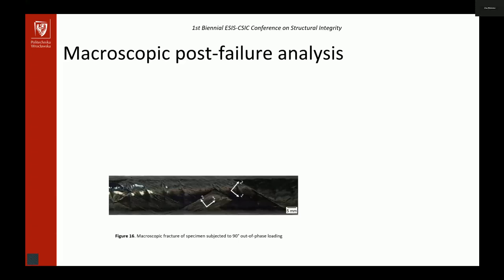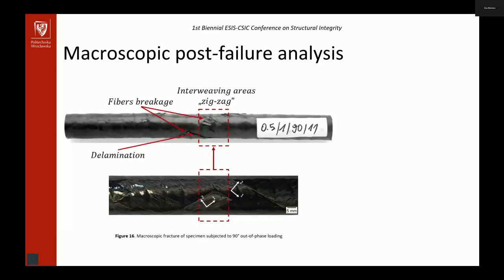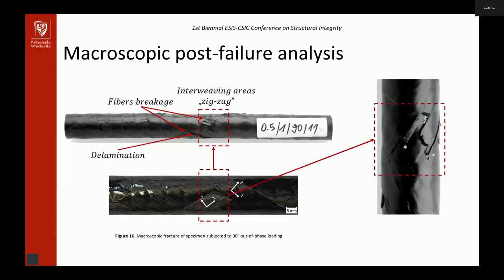Now we did macroscopic post-failure analysis, and in all specimens that we tested, the crucial area was this interweaving area, where the damage was observed. Of course, it was the final failure of this composite. We see that there was fiber breakage, which is quite obvious. But besides this, we observe delamination between the layers. I would like to add that for this specimen, the fiber orientation is plus minus 30 degrees.